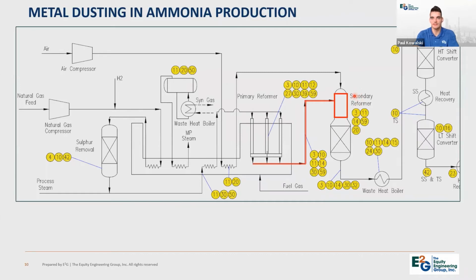And of course, with the high temperatures, it can be as high as 1800 degrees Fahrenheit. This material is also refractory lined. And then on top of the refractory, there is what's called a burner liner, which is installed to help protect the refractory from any sort of erosion or damage. And that burner liner is typically constructed of an Inconel material or a high nickel based alloy.